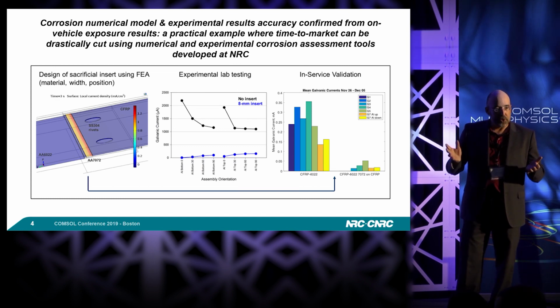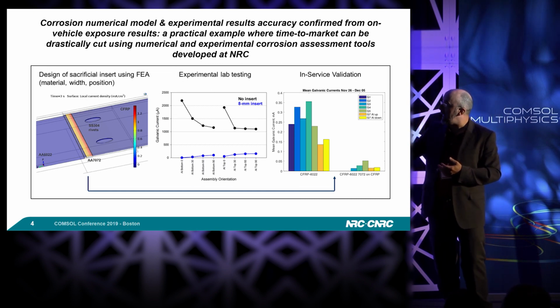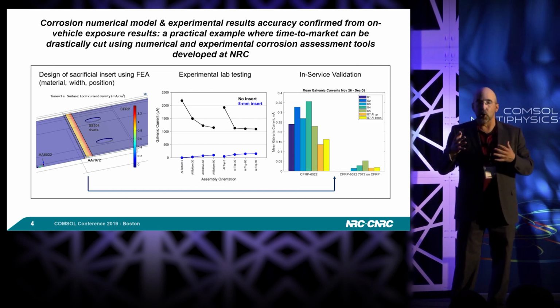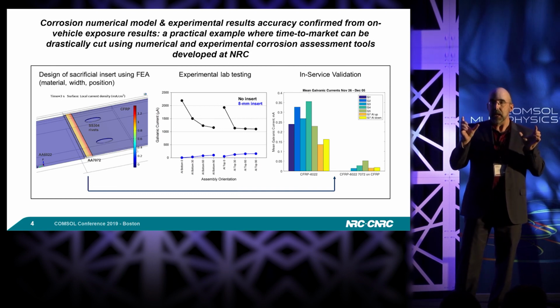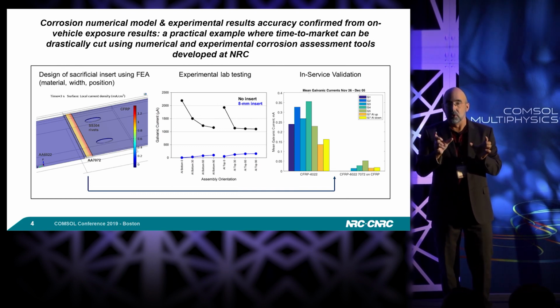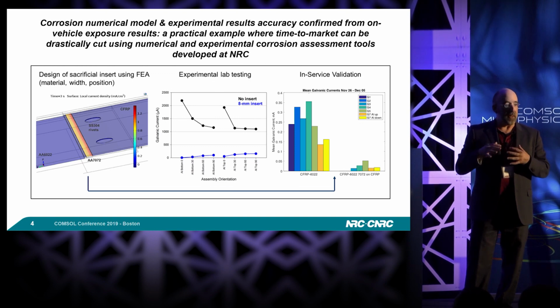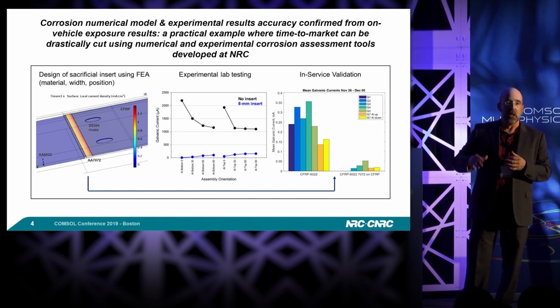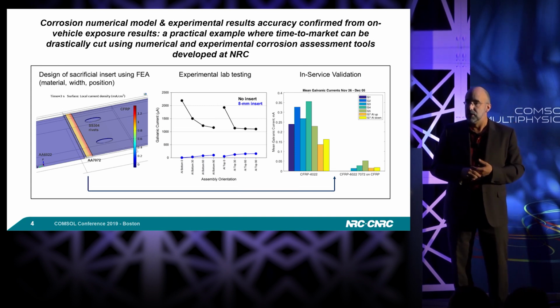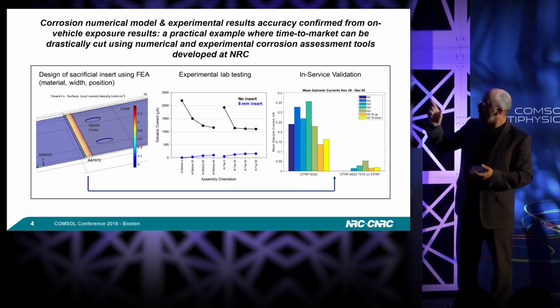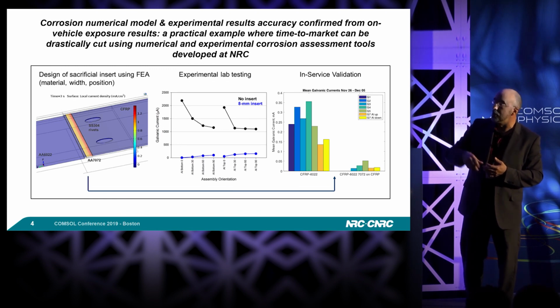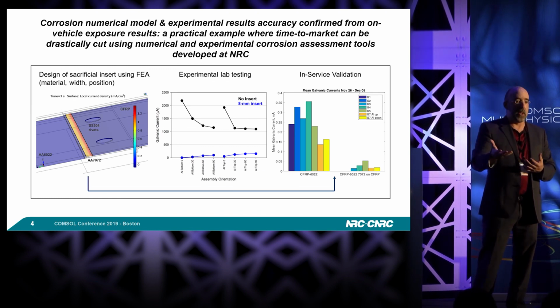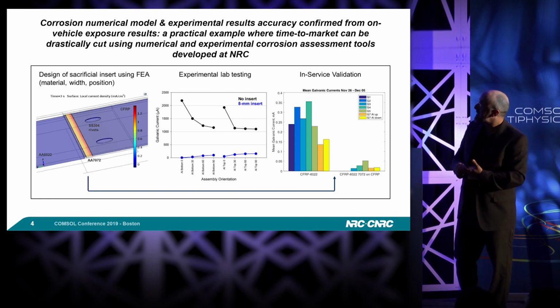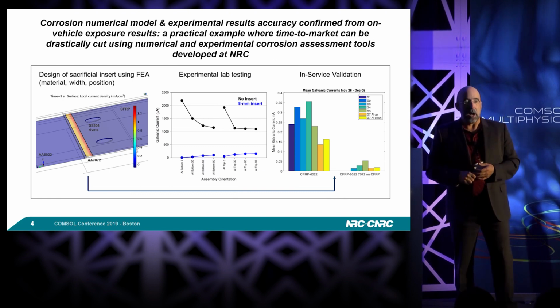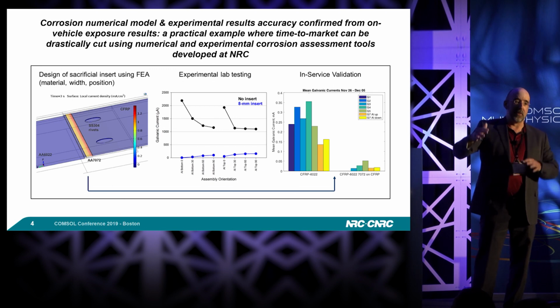In simulation, it works. We go into the lab, in black, you have the galvanic current that will flow between your two structural materials. You see it is pretty high. If you add the insert, you have the curve in blue. You see that you drastically cut the galvanic current. So in the lab, it works. Does it work in the field? We put the assemblies you see on the left, we build them, and we put them on vehicles at seven different locations: behind the mud flap, over a wheel, in front of the wheel.